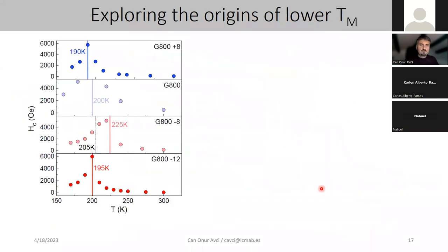And we wanted to explore the origin of this lower magnetic compensation. We thought, okay, if there is some additional scattering inside the chamber during the deposition, scattering from the argon plasma, and if that scattering is element selective, meaning you have more scattering for terbium and less for iron, maybe you get some off stoichiometry. We tried to grow films with different target to sample distance, the one that I mentioned before. But we did not see a systematic change in the compensation temperature. They are all fluctuating around 200 Kelvin plus or minus 20 Kelvin.